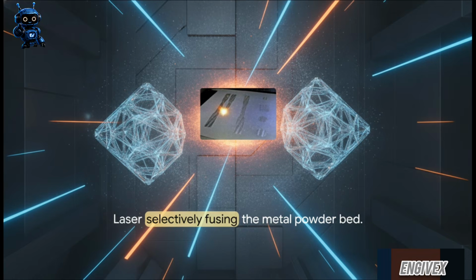This is selective laser melting, or SLM. A high-powered laser is selectively irradiating the powder bed, completely melting the metal into a fully liquid state. This is what creates that beautifully solid monolithic grain structure. But there's a catch. If the extreme thermal fluctuation during this process isn't managed perfectly, it causes severe residual stress, warping, and even microscopic porosity hidden inside the metal.